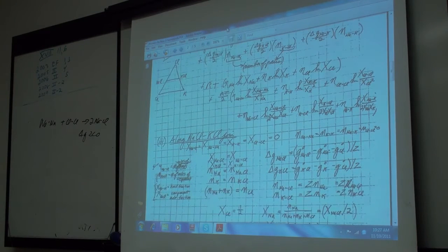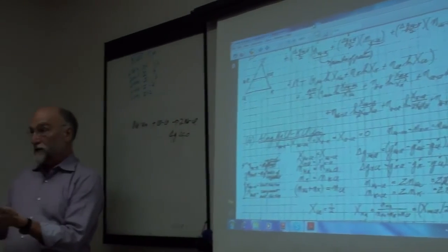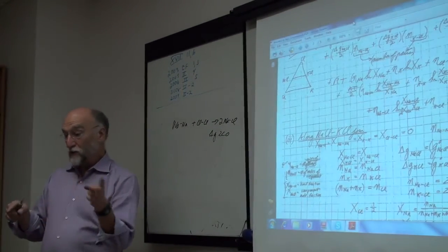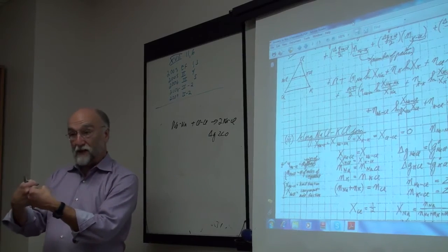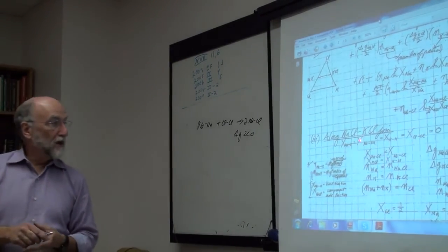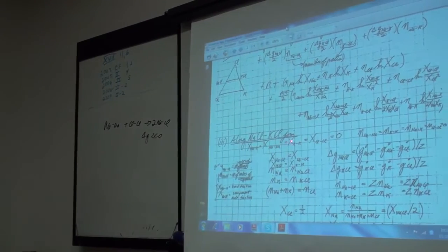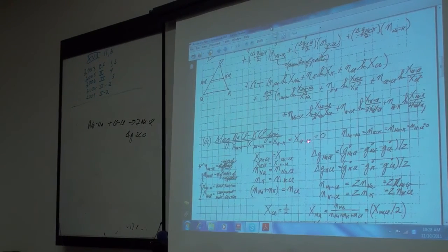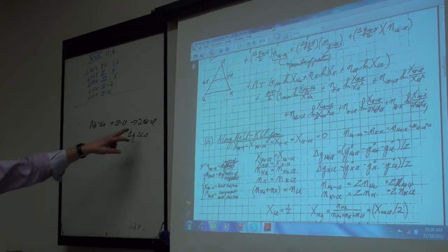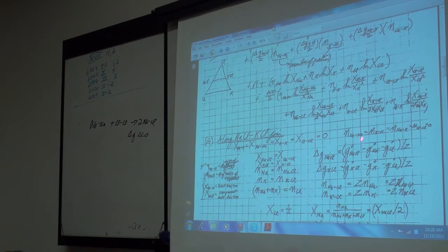Okay, so along the sodium chloride, potassium chloride join, when you make this thing, remember this is completely shifted to the right. So all the bonds are either sodium-chlorine or potassium-chlorine bonds. There's no cation, no potassium is next to a sodium. So the number of sodium-potassium bonds, sodium-sodium bonds, and potassium-potassium bonds is 0, if these delta G's are negative enough.